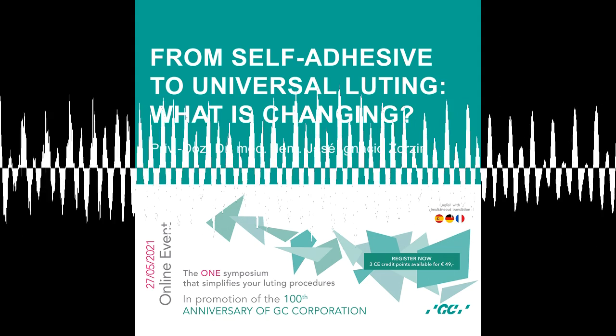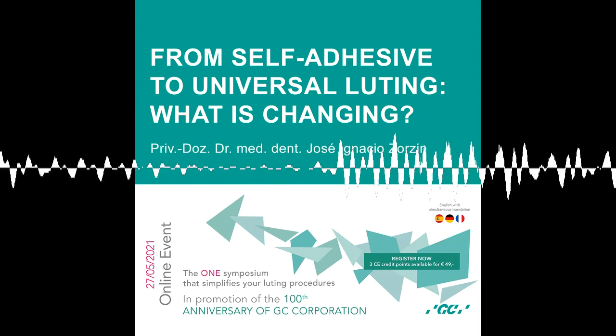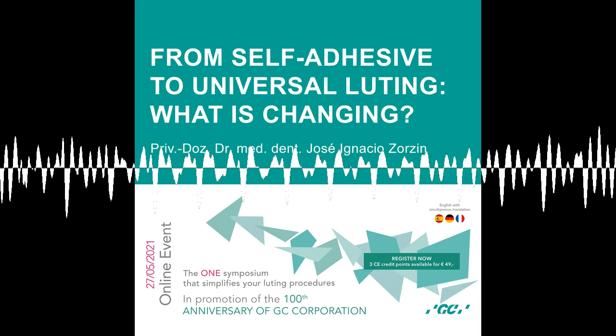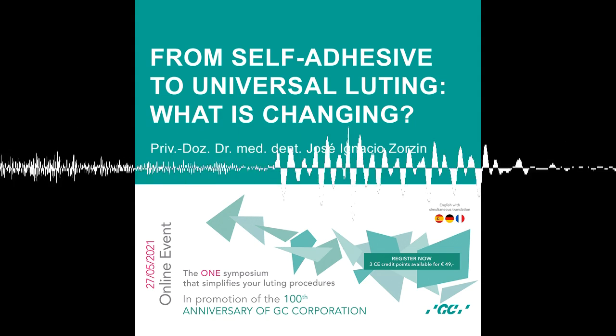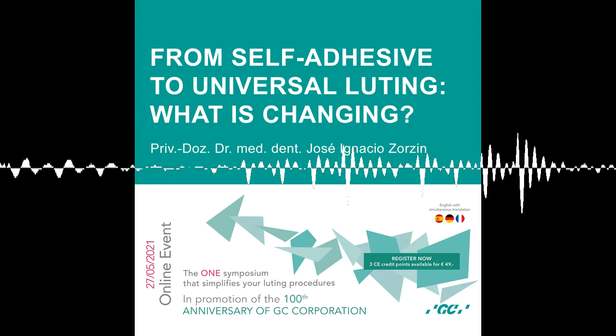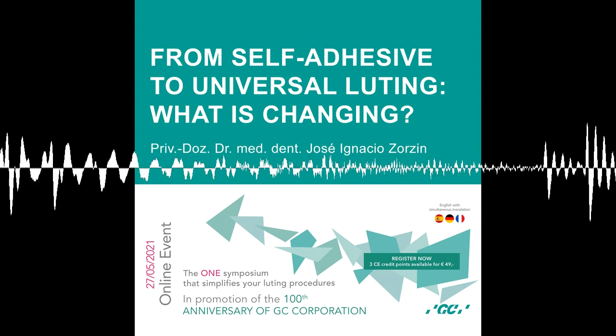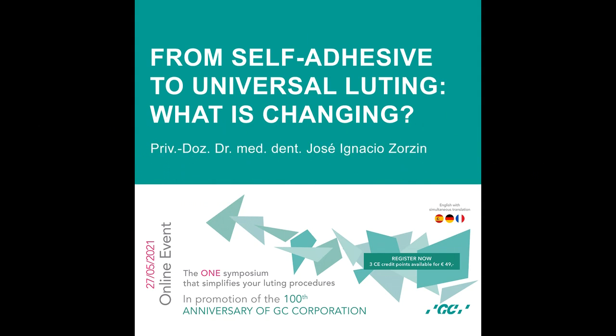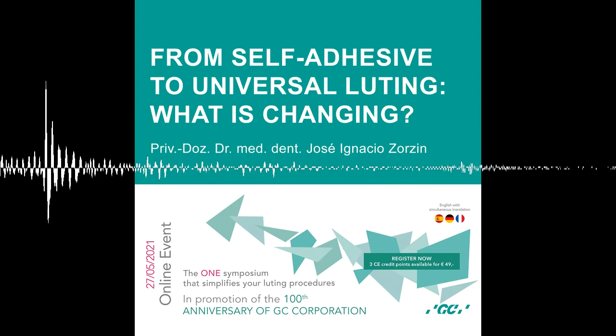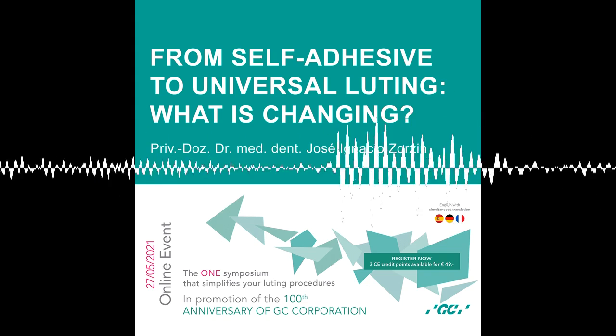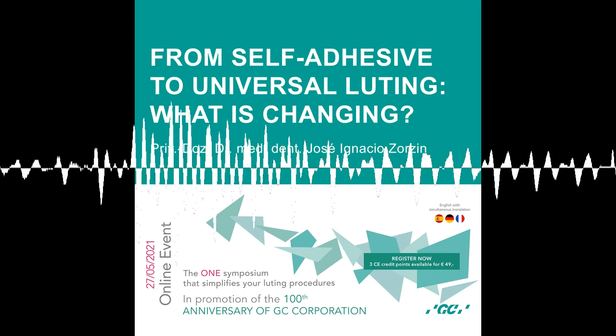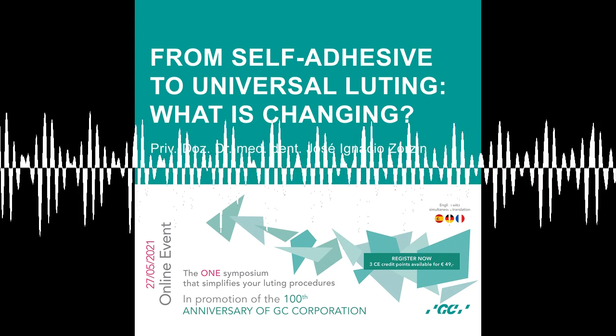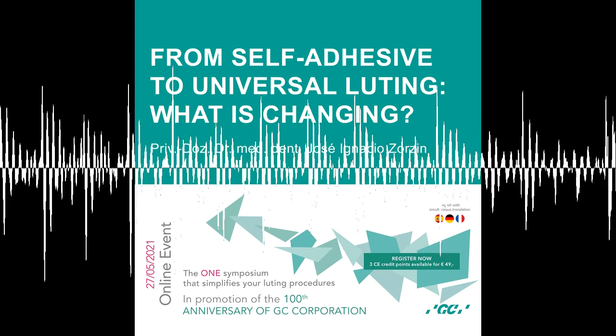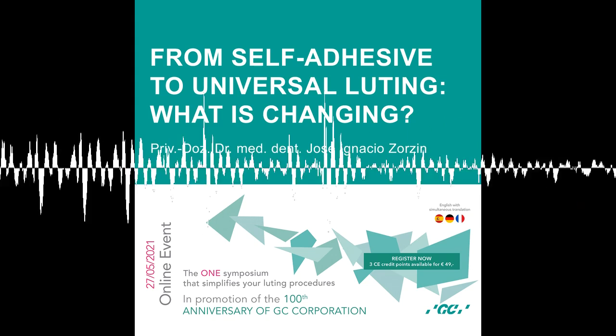Are there any alternatives to the glycerin gel to get rid of this oxygen inhibition layer? You could polish it away, but this is not practicable if you're doing it, for example, on a crown or the margin of an inlay. And you don't want to have a gap. You just want to have the perfect seal, a perfect, ideal, even resin gap between your two substrates and your restoration. So trying to avoid this gap by putting an air block on it would be the ideal.